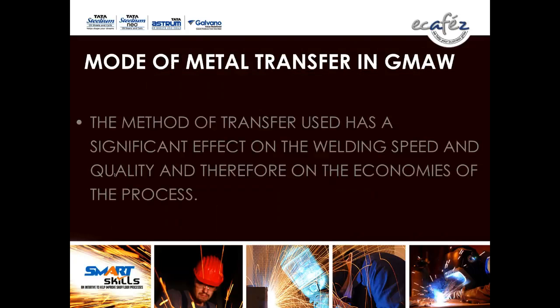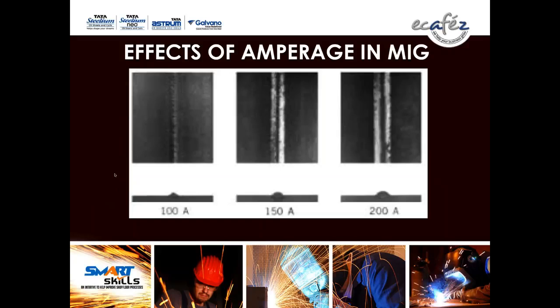Mode of metal transfer in GMAW. The method of transfer used has a significant effect on the welding speed and quality, and therefore the economics of the process. See the effects of amperage in the MIG process: use 100 amps, bad quality weld; use 150 amps, slightly improved; but best to use 200 amps, because spray transfer will start from this. So you can get a high quality weld by using spray transfer.